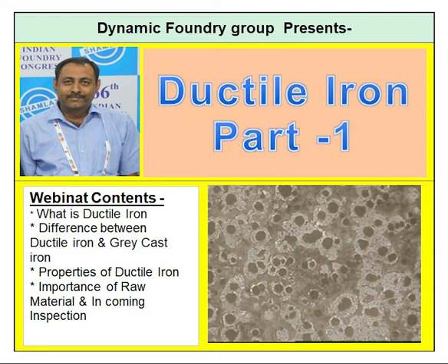Base metal chemistry. What should be the base metal chemistry? The carbon should be 3.7 to 4%. Final carbon 3.4 to 3.7% after the treatment. Silicon you can keep 1.4 to 1.7, and finally you can get 2.4 to 2.7 after the treatment and post inoculation. Manganese, if you have to keep 0.5, I will say that you have to add only at the end,